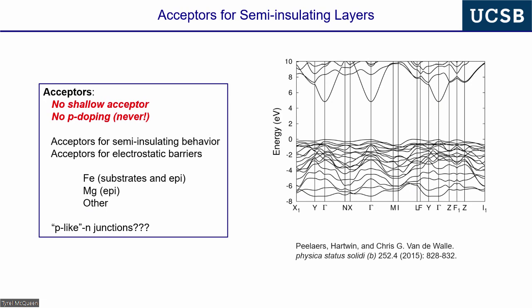But in semiconductor devices, we still need semi-insulating behavior. The substrates used today that are semi-insulating are iron doped, with iron as a deep acceptor. So the iron level is somewhere in the gap, and if there are unintentional donors, they transfer their charge to the iron. The iron is miles and miles from the valence band maximum. You can't ionize electrons to it. So semi-insulating substrates are typically iron doped.